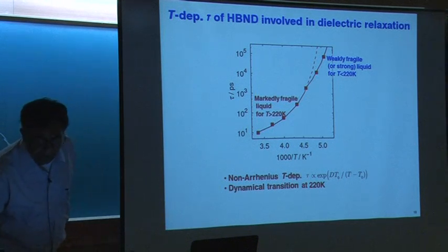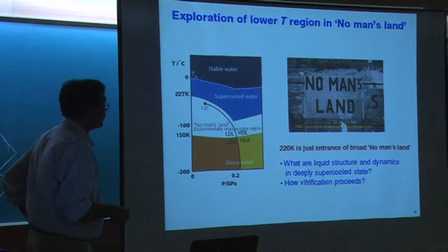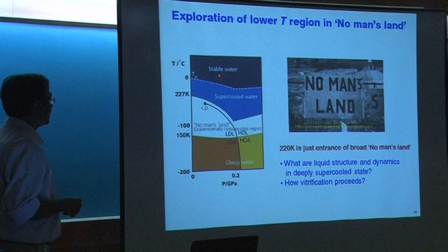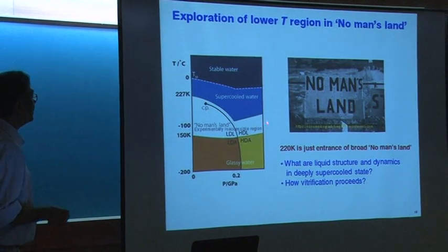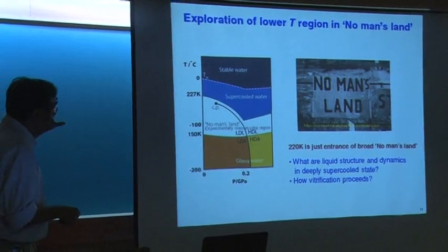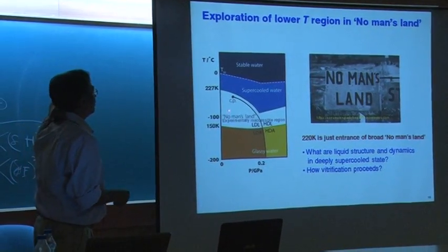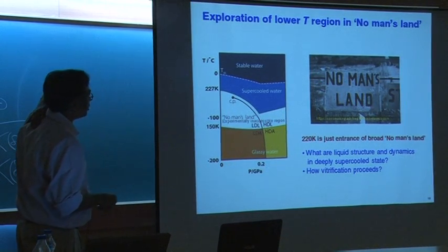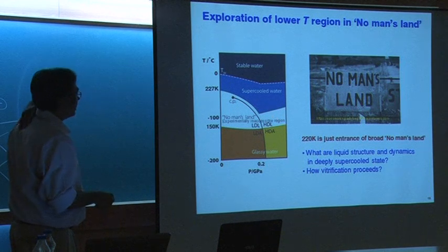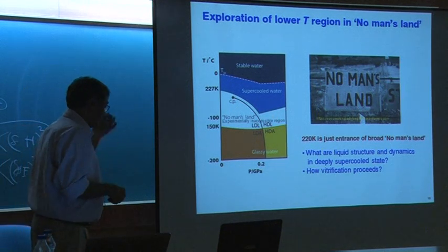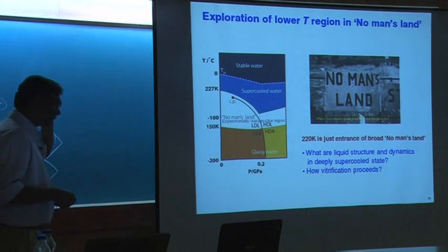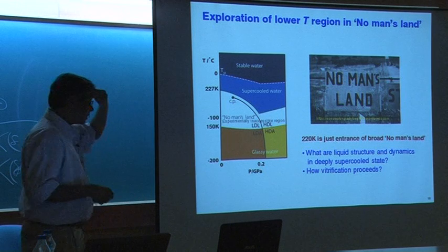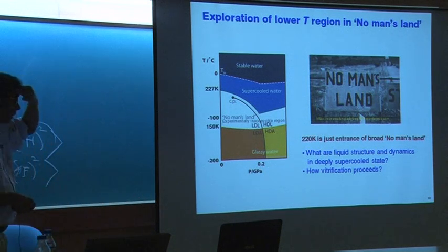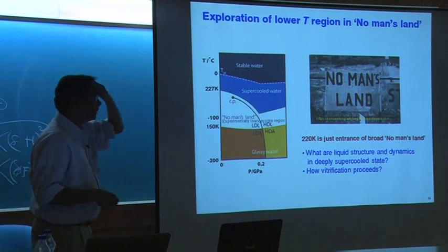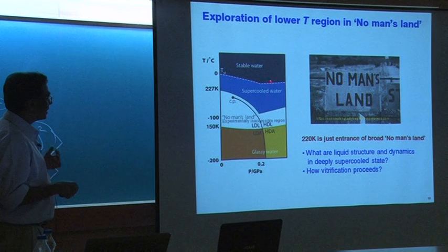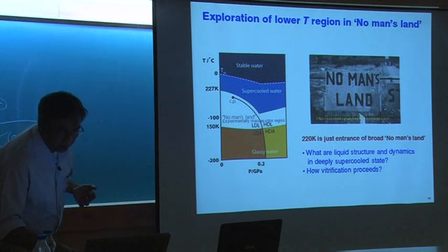And this is the mechanism that one is trying to find out, that there is a no man's land which we don't know. Water, stable water, our water, goes to supercooled, then this region is not accessible to experiment, and as I told you, there is lots of interpretation of what is going on here, lots of interpretation of the reason for the crossover. One of them considers it a liquid-liquid transition, another says it is a weakly first order transition, one more says, what we believe in, that there is a percolation transition, then there is something called the singularity free interpretation. So there are lots of very major papers on that.